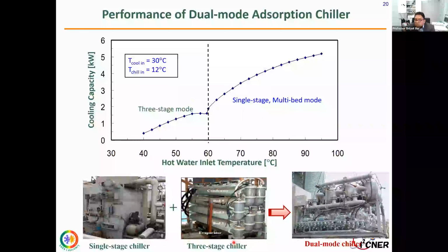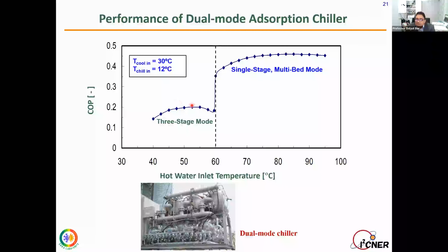So in any conditions it can operate. If it is a good sunny day, it will give you more cooling energy. If it is less, it will also give you cooling energy. But if it is only a single stage cycle, it cannot work in this temperature range. Same for the COP values also. With the COP for the single stage, we can get experimental values of about 0.47, but with 3-stage mode, it is only 0.2. But here you can see our outside temperature is 30 degree, our heat source is 40, only a 10 degree temperature difference, and we can get our cooling capacity and also COP values, which is very, very important and interesting as well.